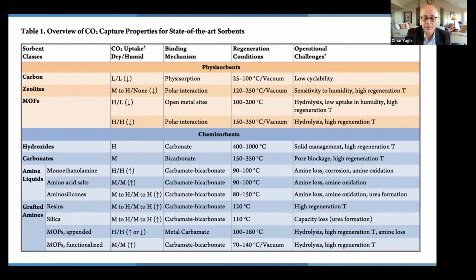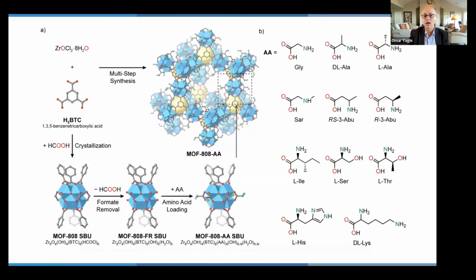In terms of stability of the materials and in terms of capacity, those are two very outstanding challenges at this point. So our approach has been to take MOFs and functionalize them. In this study, we have been functionalizing them with amino acids. The amino acid has a carboxylate on one end that hooks up to the zirconium in the structure in strong bonds, so that doesn't come off. And the amine group is selective to extracting CO2. So this is what we are able to do.